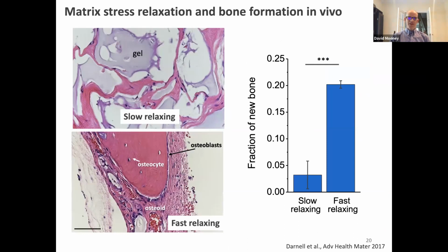Now, to further confirm this, Max took, again, a small number of stem cells, put them in gels that were identical other than the rate of stress relaxation, and implanted them into cranial defects in rodents, and demonstrated that the amount of new bone formation was much greater when the gels exhibited this rapid relaxation as versus the slowly relaxing gels of matched modulus and adhesivity. So this demonstrates nicely that the time-dependent or viscoelastic behavior of these materials is a tremendously important signal to the cells in the body and in the laboratory.